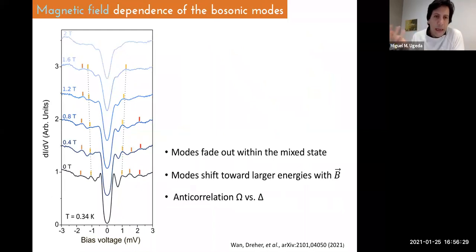So we also studied the evolution of these features with a magnetic field. The critical field of this material is around 2.2 Tesla or so. So here I show you a set of data where you can see in this case the first three modes for empty states and two modes for occupied states and their evolution with the magnetic field. So as you can see, these modes also fade out within the mixed state. So before the critical field, or the second critical field, these modes are totally gone or disappear.